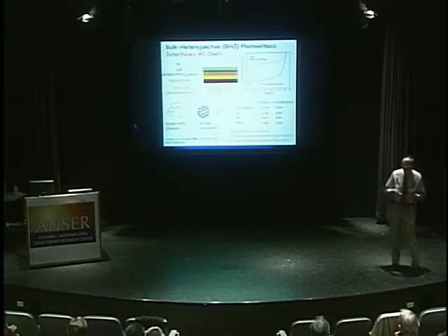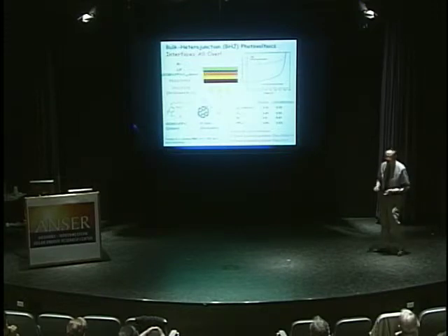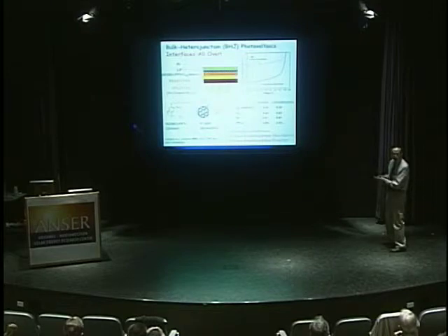It's electrically inhomogeneous. It's really not a solution. It's a suspension. If ITO is bad, PEDOT is even worse. Yet, as we agreed on at lunch, nobody seems to have anything better. How much does this limit the performance? I'll talk about that. And then here's our blend. Here's lithium fluoride, usually put here, and there are about 6 different theories why you need lithium fluoride, other than that it helps, and then the aluminum cathode.